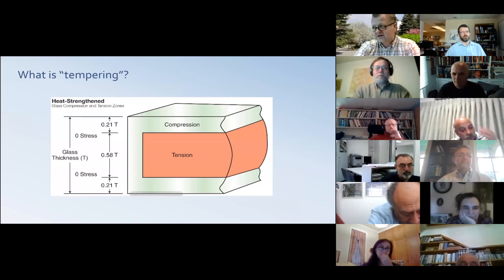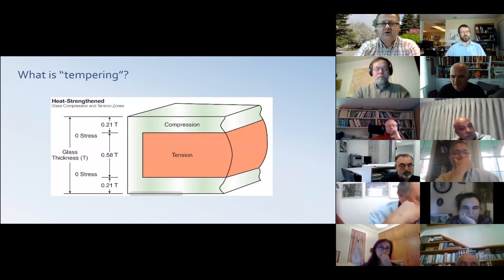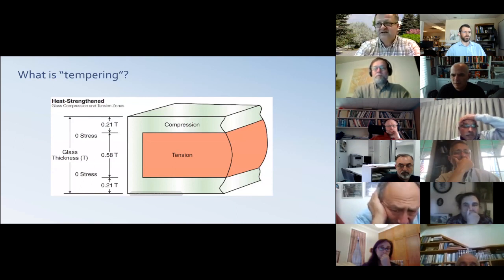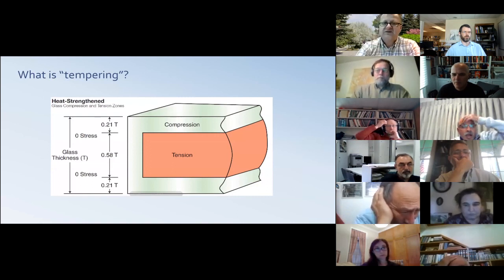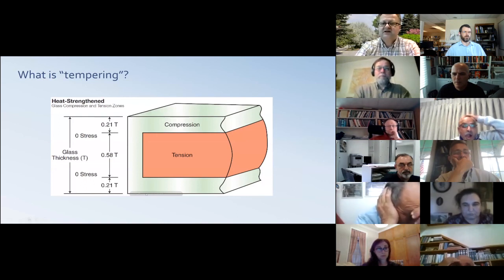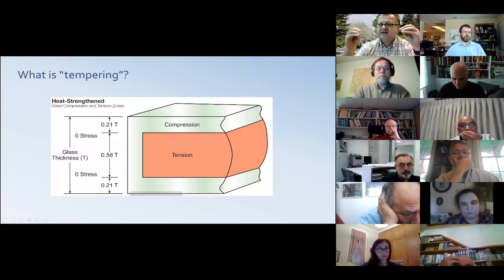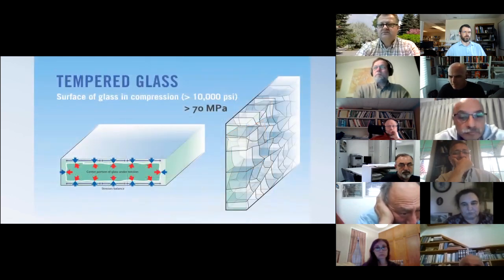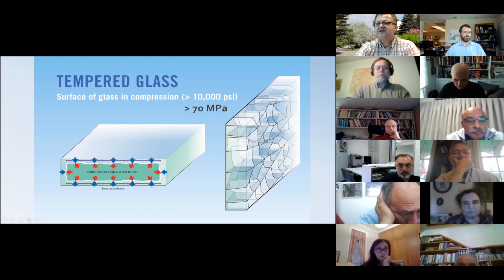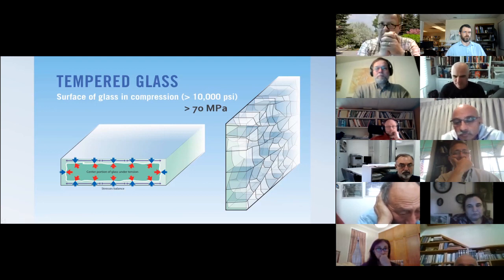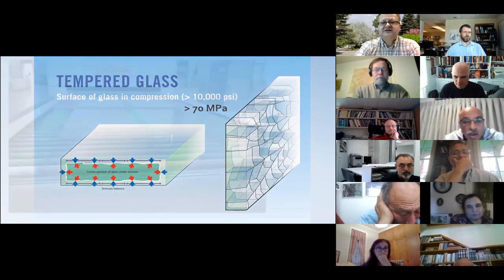Tempering is a strange act on glass that nowadays, for example, car windows are like that. They are higher strength. Actually, it is the ordinary glass, but it just went through some process. So when this is done, the outer layer is under compression and the inner layer is in tension. So because of that, when it breaks, it just tears up into little pieces, and people use some transparent material on both sides so that when it cracks, it doesn't shed into pieces.